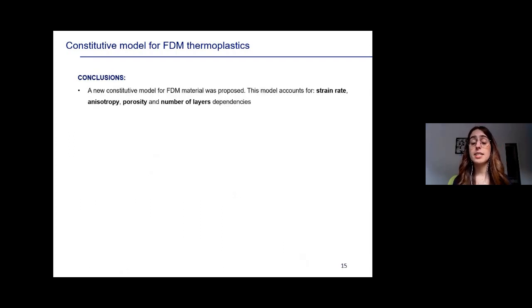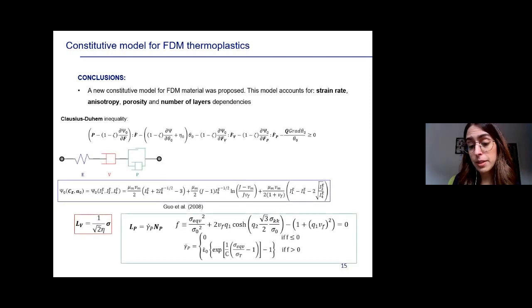As a conclusion of this last part, I would like to say that we propose a new constitutive model for fused deposition modeling materials with finite deformations. The constitutive relations of this model are derived from energy potentials within a thermodynamically consistent framework, and we take into account different dependencies such as the strain rate, the anisotropy due to the additive manufacturing process, here we have the direction in which the components are manufactured, the porosity, which at the same time is influenced by the layer height and other printing parameters, and also the number of layers dependency.